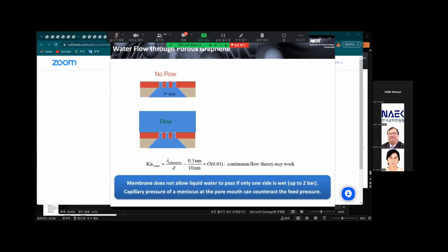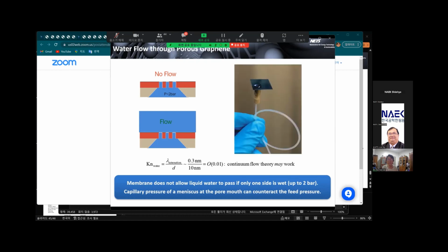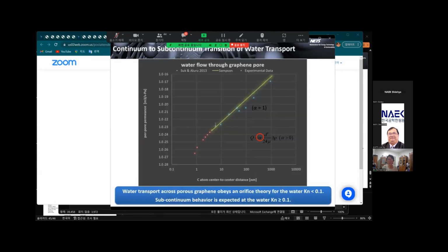What about liquid transport across a two-dimensional orifice? Because of capillarity, liquid water did not cross over the graphene membrane if one side is dry. Once we wet both sides of the graphene membrane, water permeation is observed even at a small fraction of a bar of pressure difference. For a pore size range over 6 nanometers, we verify that Sampson's formula works well in predicting the liquid flux. For pores smaller than 6 nanometers, on the other hand, Professor Aluru's simulation has predicted a deviation from Sampsonian dynamics as pore size approaches 1 nanometer especially.